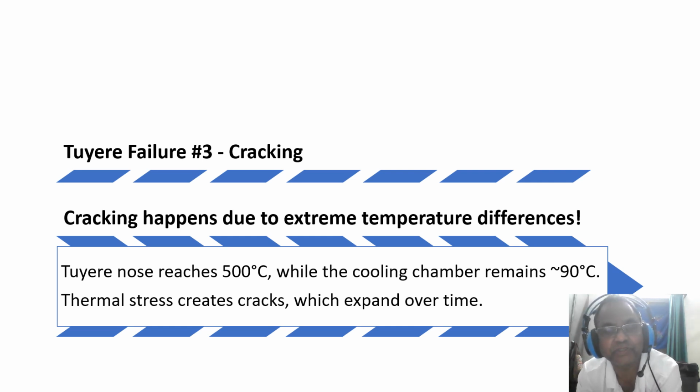We see that such cracks are somewhere very clearly visible, and somewhere they have just started nucleating. As we can see, in a number of places the crack gap is more, somewhere the crack gap is less. This leads to thermal stress, and thermal stress creates such cracks, which grow slowly, deeper and deeper, eventually leading to failure.